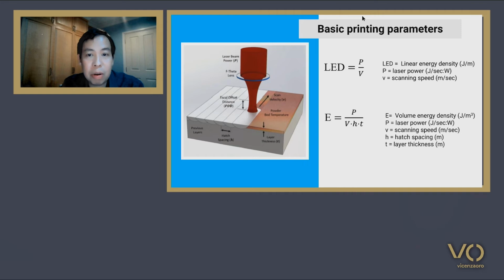So the basic printing parameters you would see here, so that we understand the same terminologies. The laser beam comes down. P is usually referred to as power, and sometimes we call it in watts. It's the joules per time, or joules per second, that is watts. And then there's a lens, and the lens that comes down here has a focal point. And then there is the focal offset distance. This is the effective length for the laser to come down and melt properly. The scan velocity is the movement of the laser. And here we have the powder bed temperature as well. As we build more and more pieces, as we build up the height in Z level, the powder bed actually becomes heated more and more.